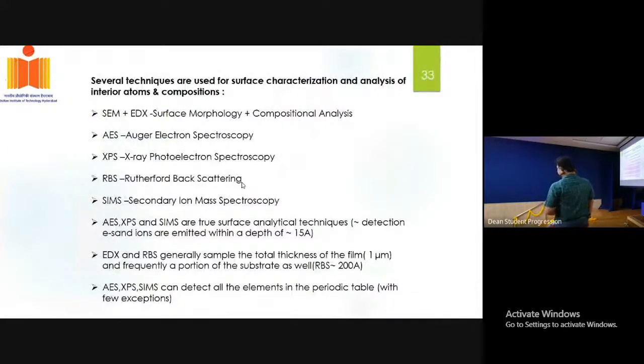So the same EDAX you can use for the surface morphology, and Auger electron spectroscopy you can also use to get the composition of the material. XPS, X-ray photoelectron spectroscopy, can also be used for the composition analysis. RBS, Rutherford backscattering, can also be used for the composition analysis. And SIMS, the secondary ion mass spectroscopy. These are all surface techniques.